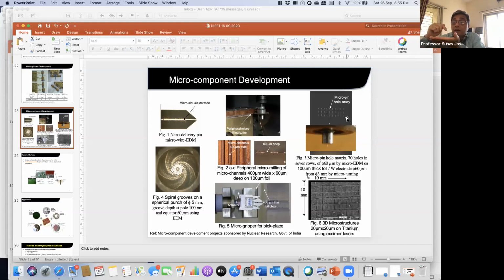So that means that when you make the first hole to the 70th hole, your electrode wear should be almost zero, or it should not be more than half a micron or something like that. So you have to optimize the EDM conditions. Once you make this small electrode of 60 micrometers, you have to optimize the process parameters. You make the parameters gentler in such a way that from the first hole to the last 70th hole, the error in the dimension should not be there. It should remain almost the same.